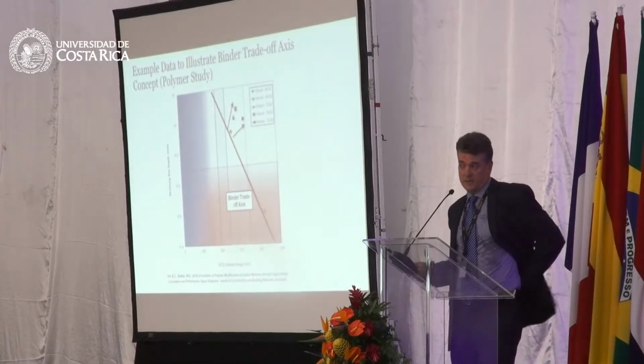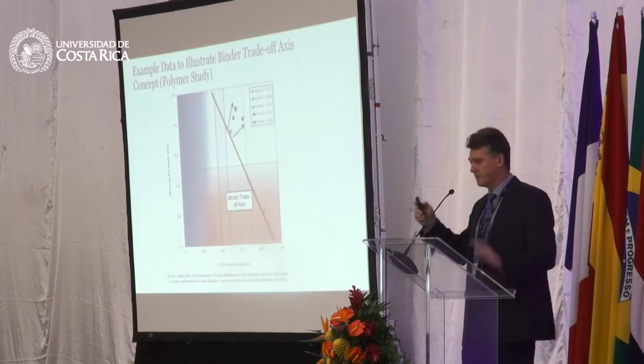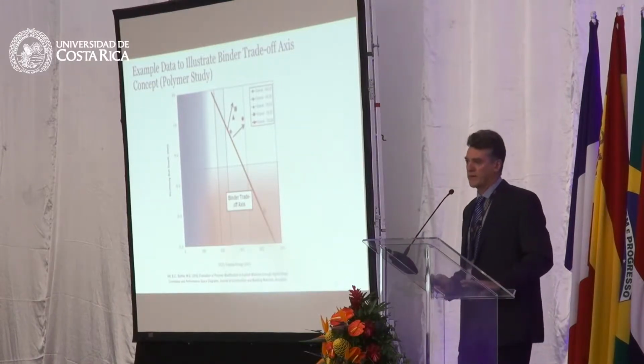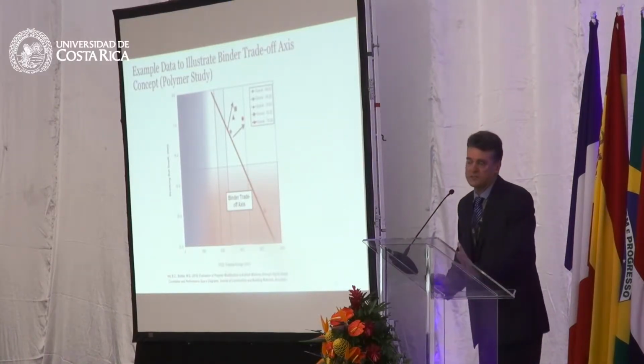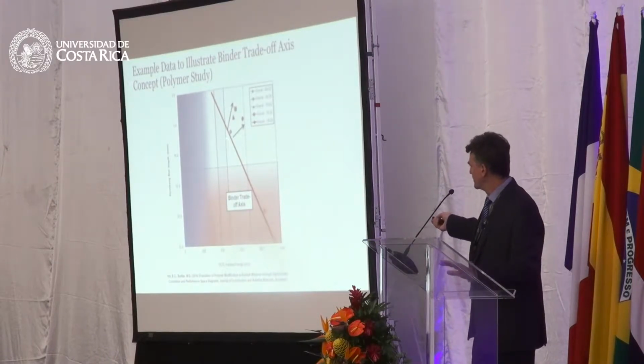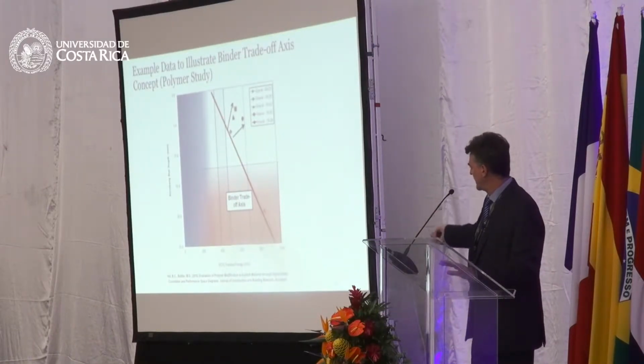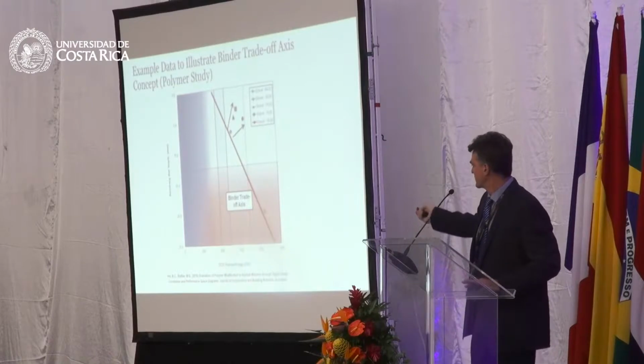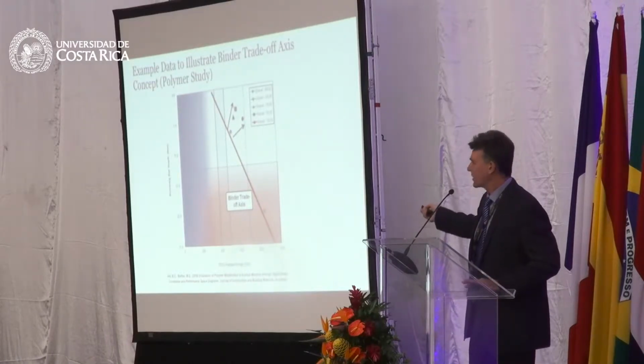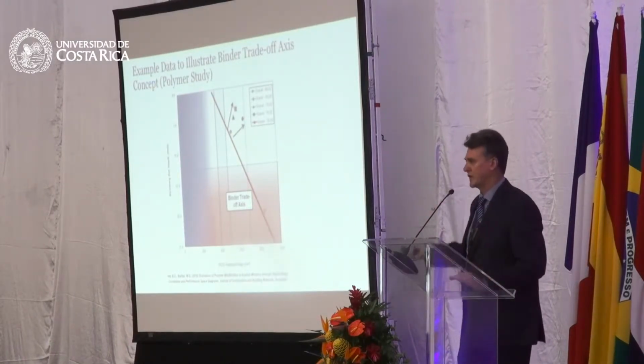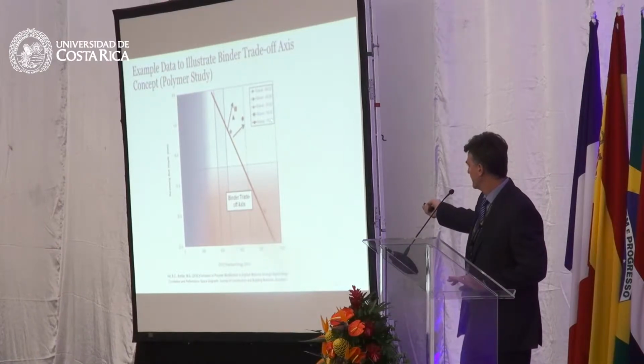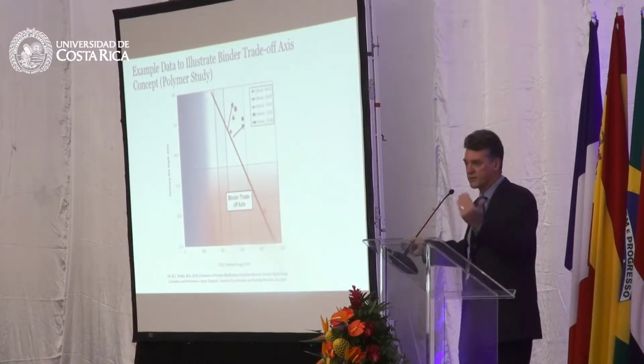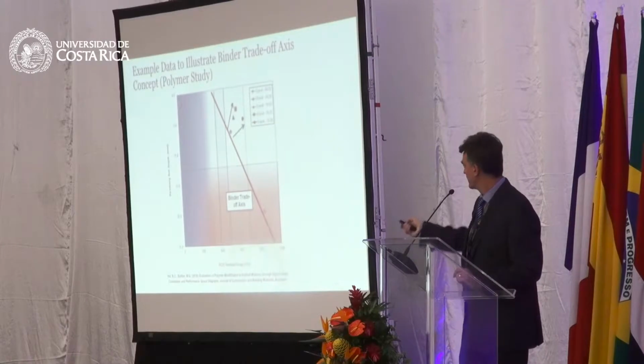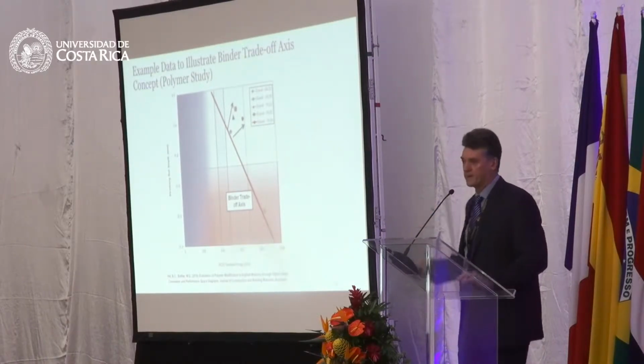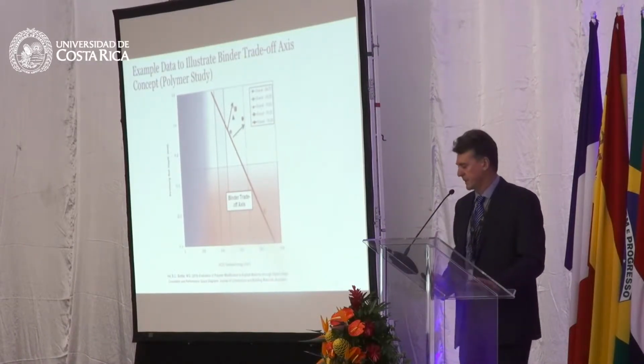But when you look at polymer modified mixtures that have a bigger spread between the high and low temperature grade, higher levels of SBS modification for instance, then you do see that instead of trading off the properties along this axis shown by the red value, then you start pushing into that performance zone that you want to be in. And so as you look at binders with more than 100 degrees Celsius spread between the high and low temperature grade, you can start to develop high traffic, high performance mixtures.